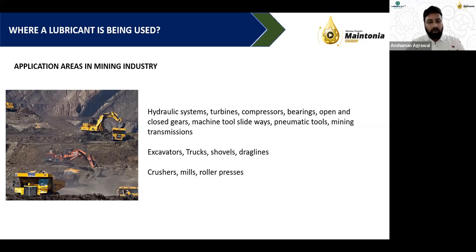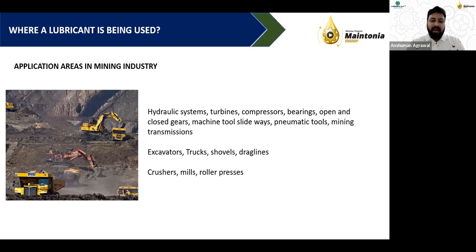All such equipment are hydraulic-based, making oil cleanliness extremely important. Coal and mineral dust in the surrounding environment is highly prone to entering equipment tanks through breathers, contaminating the oil. Solid particulate contamination can lead to sludge formation, oxidation products, varnish, and acid degradation products — all of which deteriorate the performance of lube or hydraulic oil.